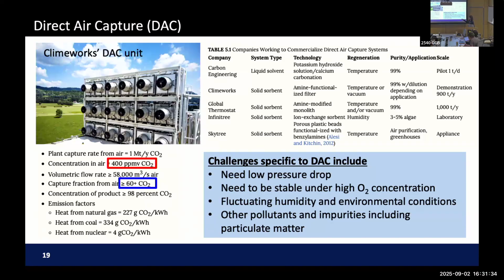And you need to deal with the high oxygen concentration in the air, remember, 21%, but the problem is that most of the materials to capture CO2 are really prone to oxidative degradation. Another challenge, as you can see, is that incoming air fluctuates. Some days are dry, some days are rainy, some days are cold, some days are hot. Even during the same day, the temperature, pressure and weather conditions can change like crazy. So it's really hard to run anything steady state, isothermal. All these are very big challenges. It's an interesting way of designing a reactor, including the environment in your system boundary.